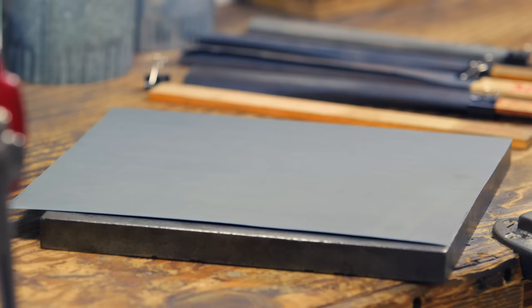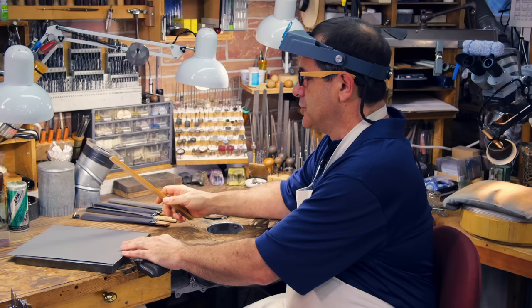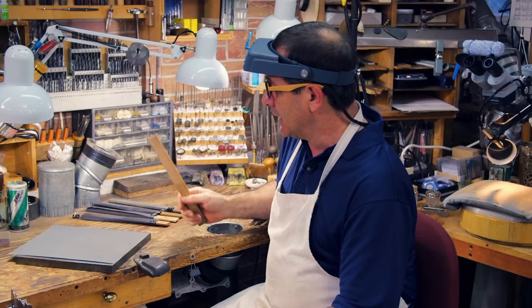But before I start I wanted to show you how I make up an abrasive stick and I'm using silicon carbide as opposed to emery. Never use emery on sterling because it will embed itself in the metal and you'll have a very difficult time removing it.